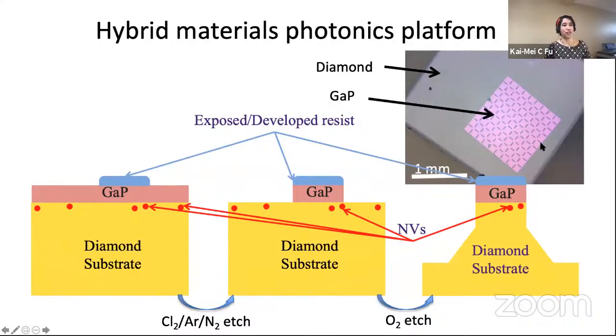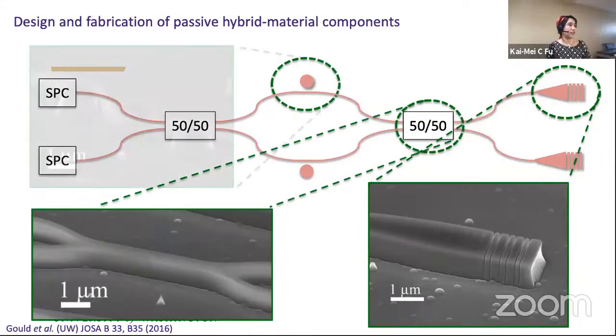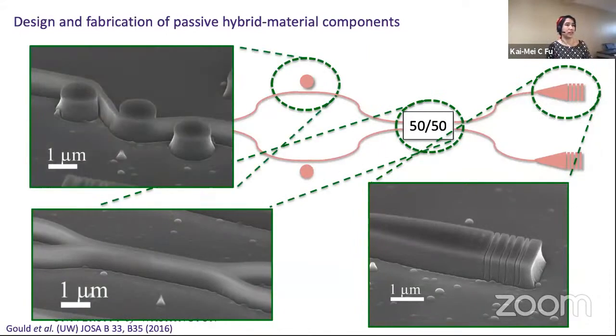Okay. In our particular system, there are so many different ways you can fabricate these types of defects. We use an optical layer that we transfer to the diamond chip, made out of gallium phosphide, and then we etch the structure into diamond. And here you can see what nanofabrication can do in terms of making these types of structures. These are actually cavities that give you Purcell enhancements in the tens or so.